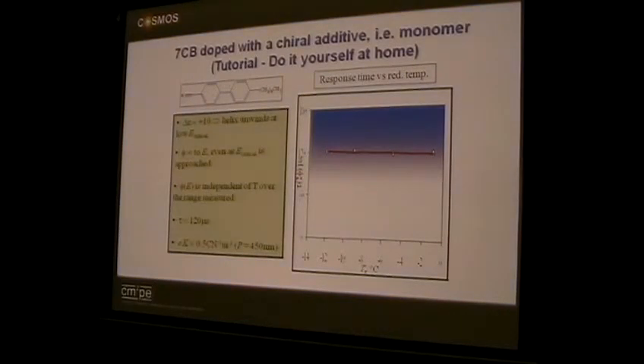Response time of that system, about 100, 120 microseconds. In a conventional nematic, that if you switched it in a twisted nematic geometry, would respond in 10 to 100 milliseconds. There it is microseconds. That's the key to the effect. E over K for that system is fairly low. Okay. So how do we overcome this?